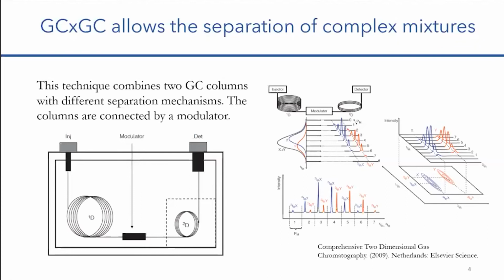But if we send this peak to a second dimension column that has different properties, right? They have different polarity, for example. We are able to see two different peaks with two different retention times. And then we are able to form this contour plot and see all the color distribution for the peaks.